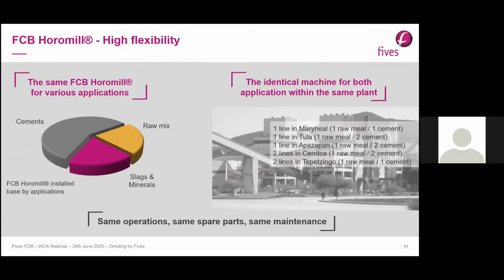So, as you have seen, the FCB Horomill can be used, thanks to its flexibility, for raw mill grinding or for cement grinding, but also in the mineral industry. On the pie chart, you can see the global distribution of existing plants. Roughly 60% of our references are for cement grinding, 20% for raw mix grinding, and the rest, roughly 20% as well, in slag and mineral grindings.